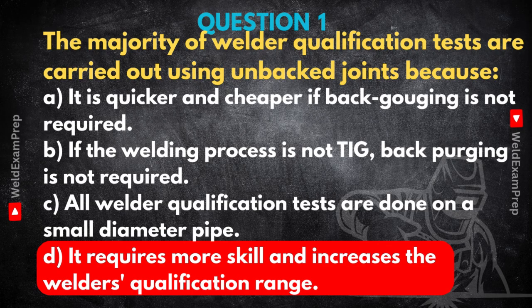It demands incredible precision. You need control over penetration, heat input, fusion, getting it just right. Without backing, any little slip up, maybe not enough penetration or too much melt through, root concavity, it's immediately obvious. So, passing this tougher test shows a consistently higher level of skill, manual dexterity, process control, the whole package. It's about proving mastery, really, at the most demanding level. And if a welder can produce a sound unbacked weld, then they're considered qualified for the easier stuff too, like joints with backing. So it significantly broadens their qualification range.